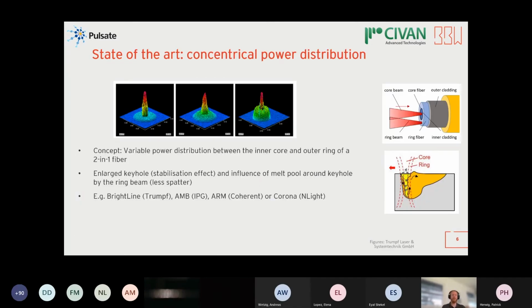Another existing strategy is the usage of superimposed intensity distribution realized by a 2-in-1 fiber. There are different comparable technologies like Brightline from Trumpf or AMB, IPG, nLIGHT, Coherent. So around the core fiber is a ring fiber, and the additional laser intensity in the ring leads to a stabilization during welding and less spatter. However, also here we are limited in the form of the superimposed beam. So only concentrically superimposed intensity distribution is possible, nothing else.